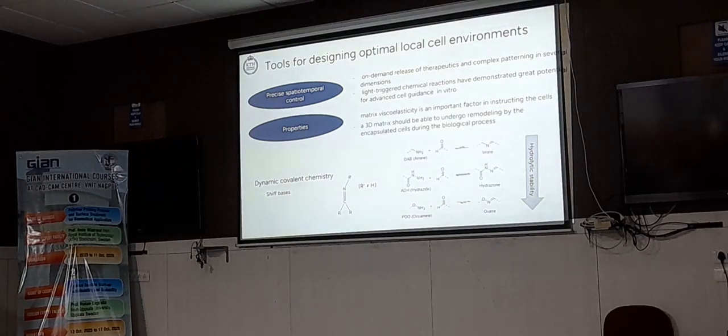Instead, if you take the other one with the amine and cross-link it with the aldehyde, then the imine won't be there for so much. So then you won't have so many cross-links. So the properties of your hydrogel will be dependent on this equilibrium and which cross-linker you actually use. So that is the basics for the whole lecture, that we will use these cross-links in order to determine the properties of the hydrogel.